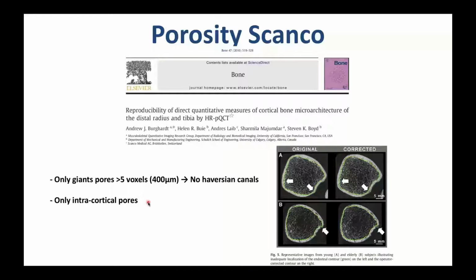In other terms, a pore that has erupted into the medullary space, so it's now an open pore, is not going to be seen or analyzed as porosity by the SCANCO algorithm. It's going to actually be analyzed as a void, or if there is still some bone in it, it's going to be analyzed as a trabecular structure, because now it's moved into the trabecular space. And that can create, of course, some lack of precision in the analysis of cortical porosity on one side and trabecular bone volume on the other.